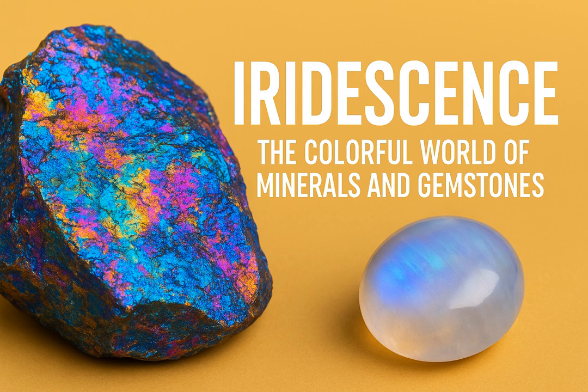So it starts with scattering for the blue, then interference from bigger layers for the other colors. That's the current thinking, yes. The combination effect that evolves as the structures form. It's also quite noteworthy that the angular spread of the reflected light, how wide the flash appears, is greatest for blue iridescence. Oh, really? Yeah, it appears about twice as wide compared to red or orange flashes. Blue also tends to remain visible longer as you turn the specimen. Which explains why those brilliant blue flashes are so prominent and persistent in Labradorite. Exactly. It often dominates its labradorescence.